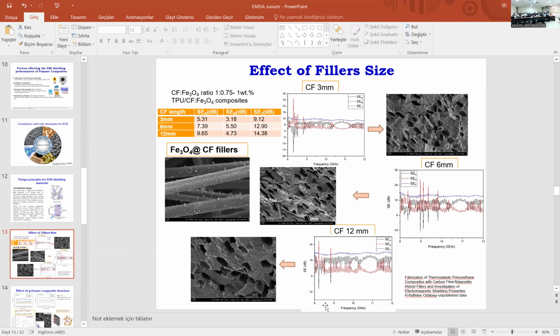Here are some examples presented about the factors affecting the EMI shielding. Here you can see as an example one of the works showing the size effect of the carbon fiber fillers. These carbon fillers contain magnetic materials. As the carbon fiber length increases within the polymer matrix, more effective and continuous pathways are formed, and this enhances charge transport and electromagnetic wave attenuation. Also, the porous structures can be seen here. These contribute to multiple reflection, resulting in higher overall EMI shielding performance.